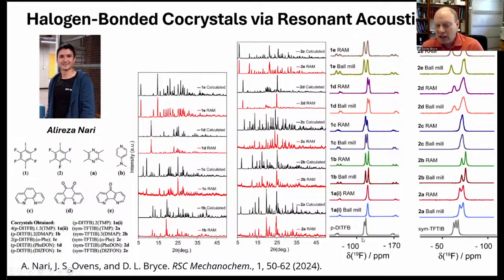This is a very sensitive probe nucleus, so we can get these spectra in a matter of a few minutes. And again, if you just take an example here, at the bottom, we have a pure donor, para-diiodotetrafluorobenzene. This is the fluorine spectrum. Bottom trace here. And if we prepare a certain co-crystal 1A by ball mill, we get a different spectrum. By RAM, we get the identical product. And you can look through by eye, and most of these are perfect matches, basically showing that yes, with RAM, we can reproduce exactly what we're getting from ball milling.